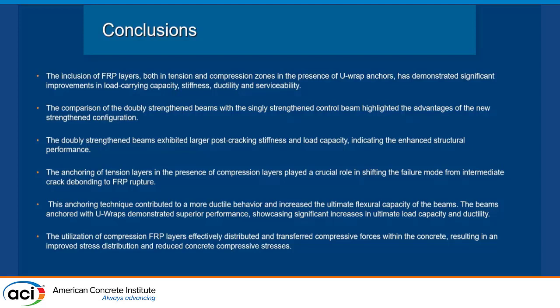So anchoring the tension layer in the presence of the compression played a crucial role in shifting the failure mode from the intermediate crack debonding to the FRP rupture. The anchoring technique contributed to a more ductile behavior and increased the ultimate flexural capacity of the beams. The beams anchored with U-wrap demonstrated superior performance, proving the significant increase in the ultimate load capacity.